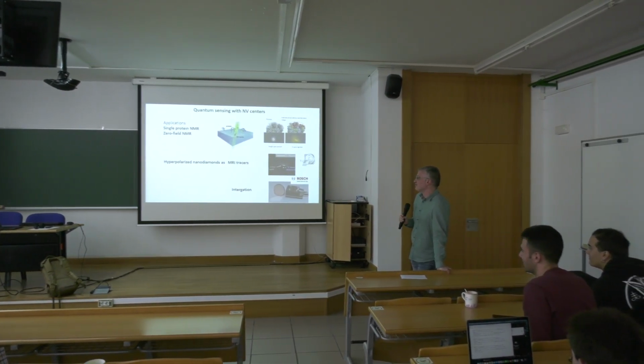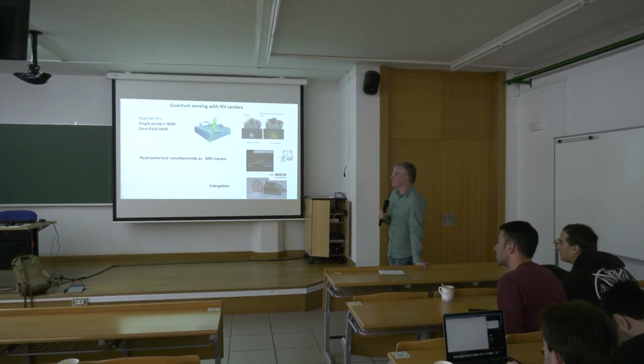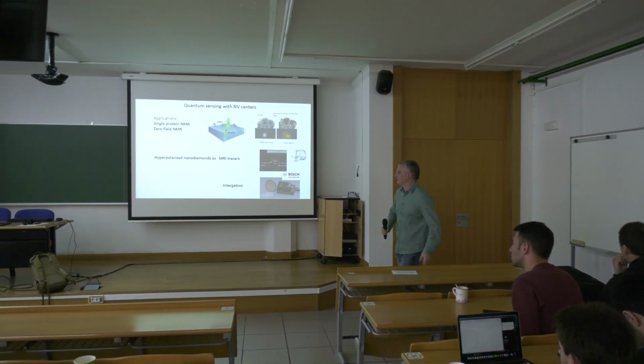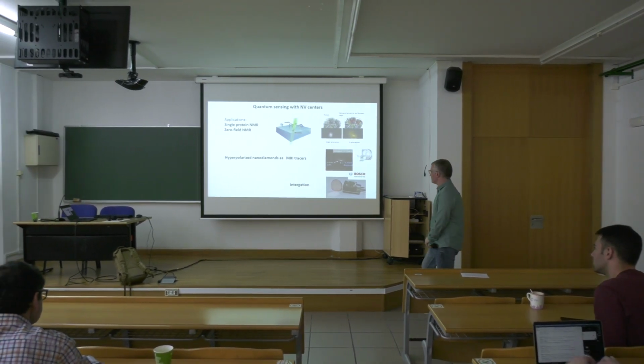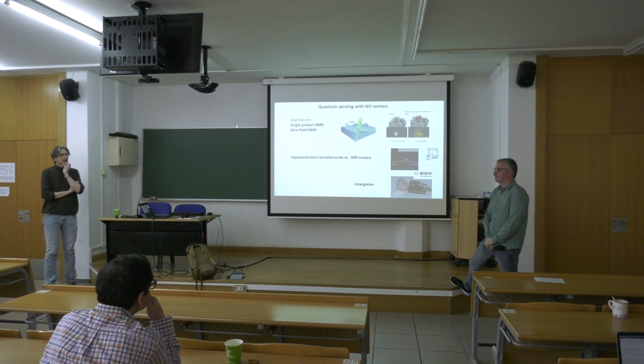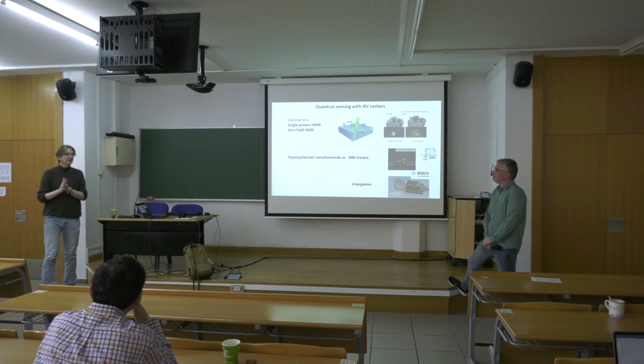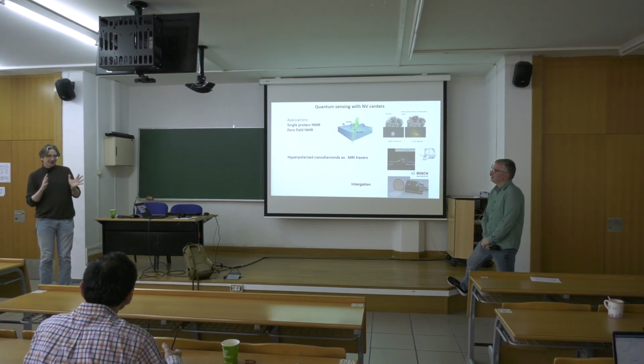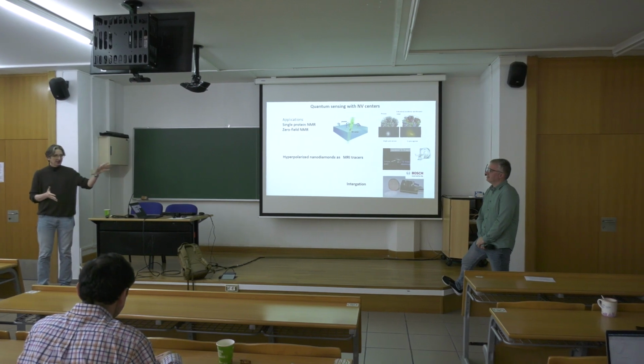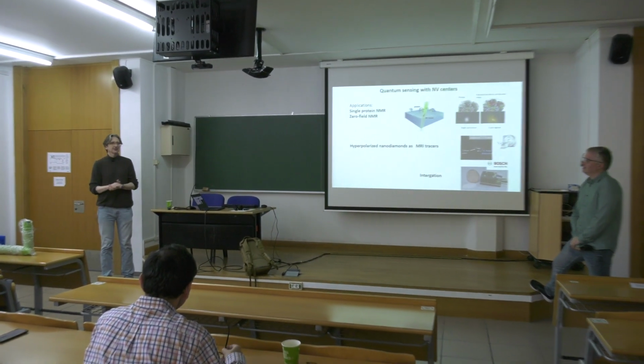So, why the NV? Are there no other defects in these solid-state devices that would make more or less the same story, or is it special? Yeah, currently I think there are many other interesting color centers, but the unique combination of a few properties, like room temperature and long coherence time, is not there for many color centers. And this pretty high contrast in optical response to magnetic fields is also not for many. An ability to create them by ion implantation is not demonstrated for many color centers.